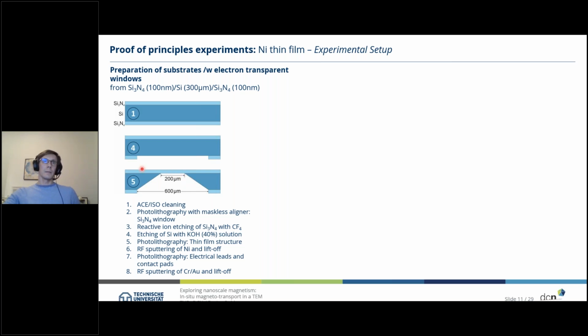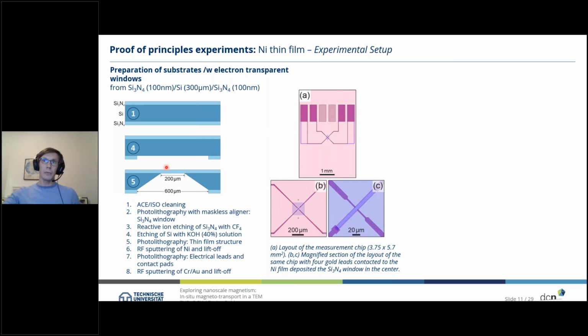And then we did photolithography to define areas where we want to have our nickel film deposited on the silicon nitride, which is shown here as the mask layout on the right hand side. So the blue is now the layout of the nickel film we want to measure. Then we deposited the nickel, did a lift off, then we did lithography again to define the different electrical leads and contact pads, where we now use 4 of our contact pads to contact the sample. And then we did the chrome gold sputtering process and the lift off again.